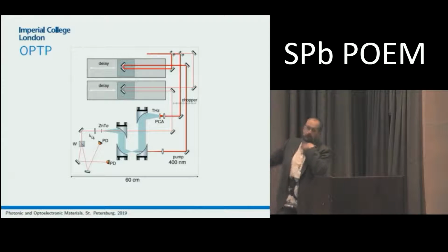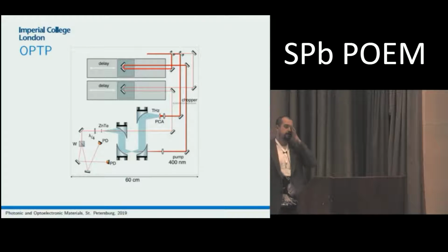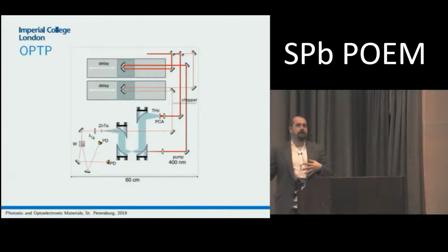Then we are using a large area photoconductive emitter, which we found to be quite efficient, a quite nice trade-off. We are using an amplified system, but the energy that is left for the terahertz setup is not really high. So using filament generation or other types of nonlinear processes would not be as efficient. But this biased large area photoconductive emitter is quite efficient and quite broadband to be employed in this setup.